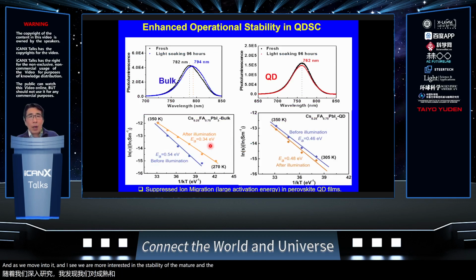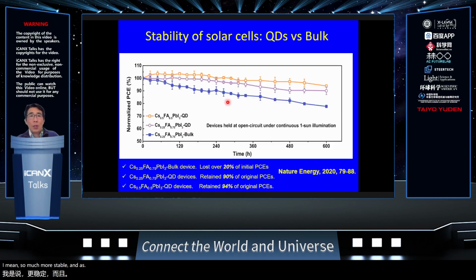And our hypothesis, or our expectation, is that by tuning the particle to a small size, we should be able to keep the material phase stable, and that's what we expected. And our measurement also proved that that's true. Basically, after getting smaller, the activation energy can become larger, that means much more stable. If we irradiate the device continuously for 600 hours, the quantum dots device still has 94% of the original PCE, but the other ones actually lost a relatively high percentage.